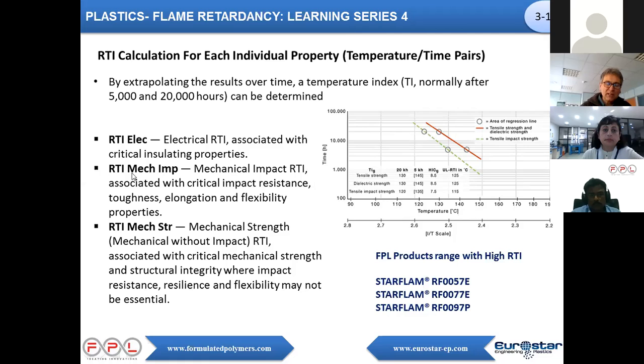So what do we determine? Basically, this is what you will see on the yellow card, 3 different properties. The electrical RTI, which is, simplifying, the continuous in use temperature for electrical properties. It's measured most of the time on dielectric strength. The RTI with impact is measured most of the time on impact bars, Charpy or ISO. And you have the mechanical strength without impact, which is most of the time measured on the tensile bars. So you have 3 important properties that can simulate the continuous in use maximum temperature for this material.